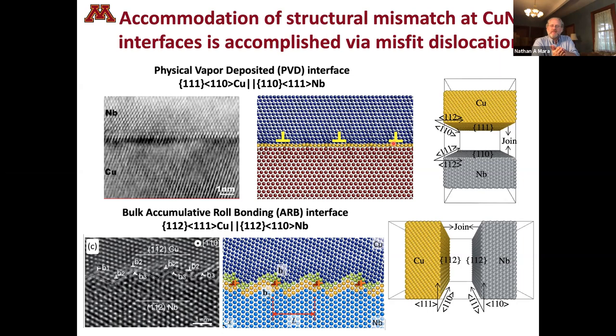And the reason is that they have these different crystal structures. So just putting them together would require huge elastic distortions at the interface to accommodate that mismatch between the two phases. So the material does what's easiest. It puts in defects. So those extra half planes that I showed that are responsible for plastic deformation, you can also put them in to just relieve the geometric mismatch between two different materials. So you can place them periodically at the interface, and that relieves that misfit strain.